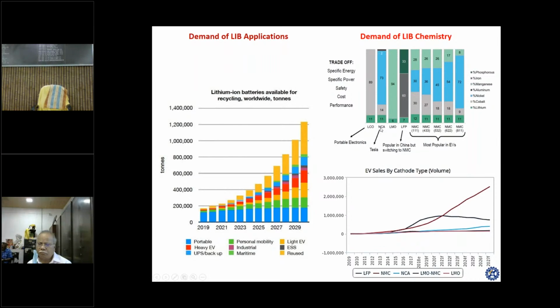And then when we move to the nickel cobalt aluminum, which is used by Tesla, it is actually governed by the nickel, but nickel is also a very, very critical metal. And in the below graph, if you see, the lithium NMC cathode, that is the nickel manganese cobalt cathode, has overtaken all the other chemistries in the recent past, and it is bound to, because the charge density and the reliability of these batteries are more than the LFP batteries primarily and the LCO batteries.